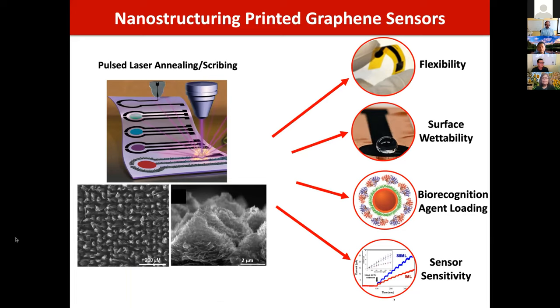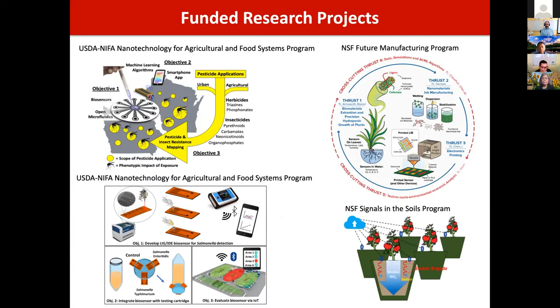We also have more surface area for biorecognition agent loading, and that improves the sensor sensitivity by four or five fold at times. All of this we can do on polymers and paper even, because this is a rapid pulse technique that won't burn up paper. So we can do it on flexible surfaces. And I'll show you a little bit that we can convert that into a wearable sensor as well.